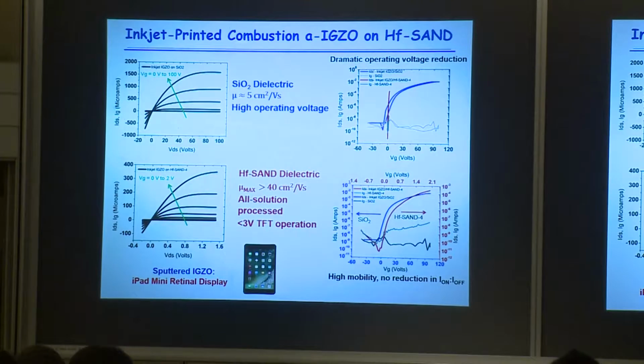But just to show you, here's the silicon dioxide gate dielectric. Pretty poor mobility. The sand dielectric, the mobility is about 8 times higher. And you can see if I look at these transfer plots, the red is the sand dielectric. And look, this is the operating voltage range. And here's silicon dioxide, and here's the operating voltage range. So you really gain a lot.